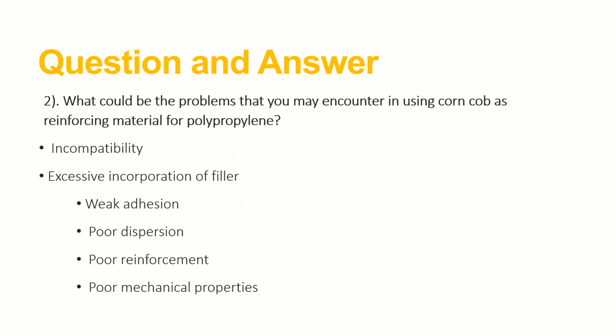It can be seen in the studies of Ramos et al. in 2019 and by Salma et al. in 2014 that the tensile strength of the corncob polypropylene composites decreases with increasing filler loading. Ramos et al. used SEM images to demonstrate poor chemical interactions between corncob particles and polypropylene macromolecular chains, proving that corncobs are heterogeneous particles scattered in a polypropylene matrix that can serve as stress concentrators.